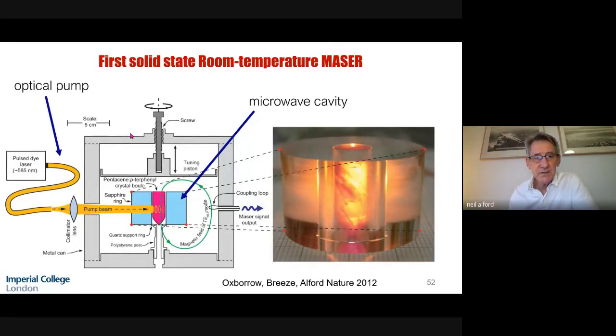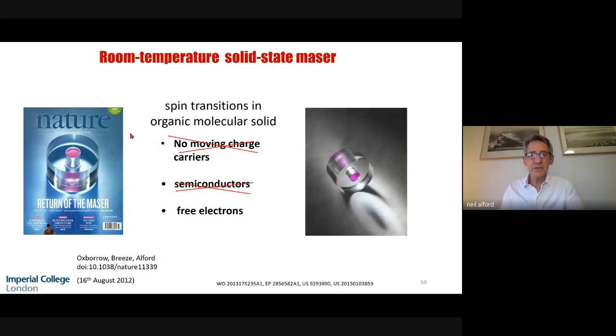And what you can see here is that we illuminated it with a pulsed dye laser, which we bought second-hand, and put it inside a copper cavity. And there's the copper cavity, and the pink thing in the middle is the pentacene within the terphenyl. And around that we put a very high Q sapphire resonator. And the result was that we were able to make the first room temperature solid state maser. And the advantage is, of course, that there's no moving charge, there's no semiconductors, just free electrons.